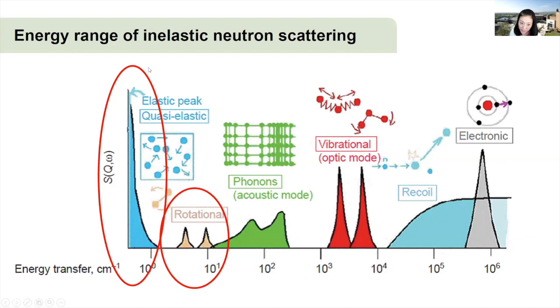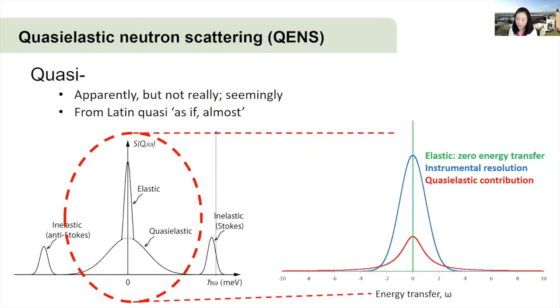And so, quasi-elastic neutron scattering offers the opportunity to look into hydrogen diffusion and the dynamics inside the pores. So what does quasi mean? Quasi means apparently, but not really. So quasi-elastic is the neutron scattering near zero energy transfer, very close to the elastic peak, but look at the broadening. The broadening of the elastic peak gives information about the dynamics of hydrogen molecules. The wider the elastic peak is, the more mobile the hydrogen molecules are.